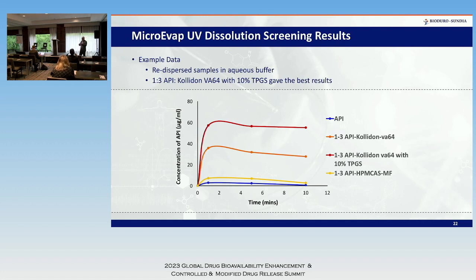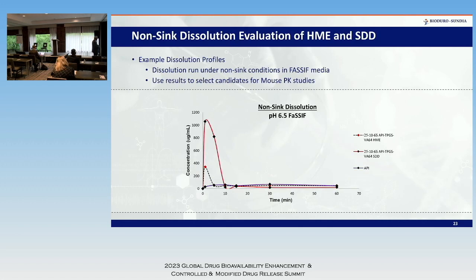But on top of that, if you look at even the Kaletra formulation in the inactive ingredients list, you will see that the surfactant from the soft gel is still there. So this product was previously a soft gel. It has changed into an amorphous solid dispersion, but they still kept the surfactant, and that's what we saw here: adding VA64 to this compound actually helped increase the solubility of this drug, and later on we showed that it also increases bioavailability.